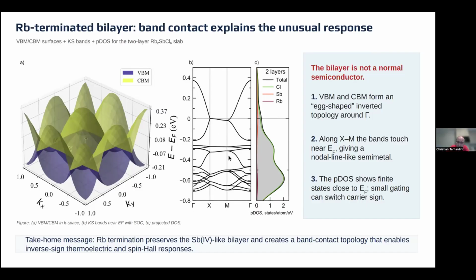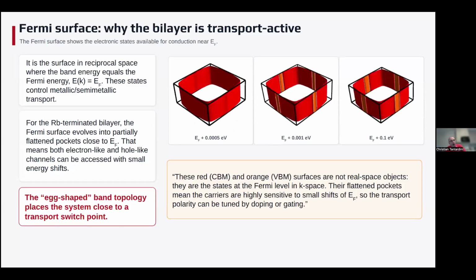So here we can see that due to this particular band structure, we expect different electronic and thermoelectric properties and also spin response. Looking more into detail at the Fermi surface, this red is the conduction band minimum, and the orange is the valence band maximum that you see here. The Fermi surface is like a map in K-space, this is the Brillouin zone of our bilayer, so that as we increase the electron volts, we see a change.